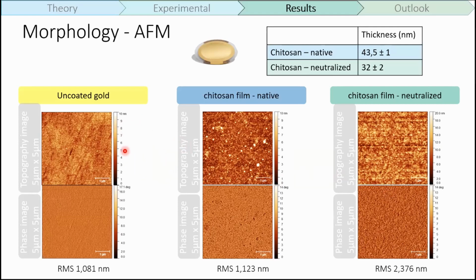We compared the bare uncoated gold crystal to the Chitosan film crystal and then to the neutralized Chitosan film. As you can see, there is some difference when comparing Chitosan native to Chitosan neutralized - the particles are getting a bit bigger. This is also observed from the roughness measurements, because the roughness of the neutralized film is slightly higher than the native film. And as we already saw from the pictures of wafers, the color got a bit lighter.